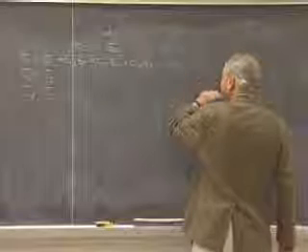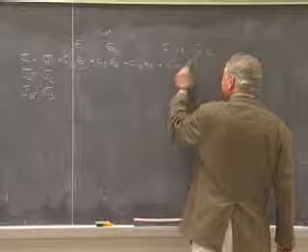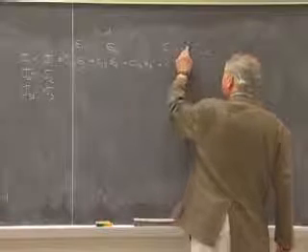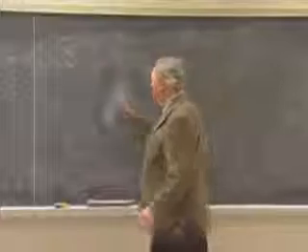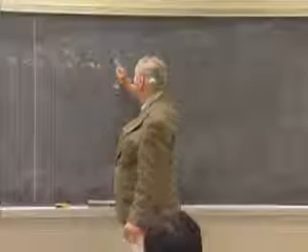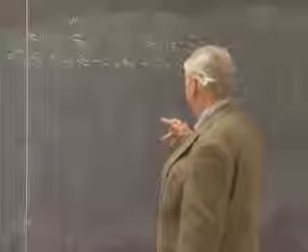And if you want to write this as a matrix, C1,4 has to be equal to the sum of these two things times epsilon 4. It's the only way you can write it as a matrix. And if you think it was bad worrying about a factor of 2 in front of half of the terms on the right-hand side of the equation, we're going to be dealing with factors of 2 for terms in the upper 3 by 3 array.